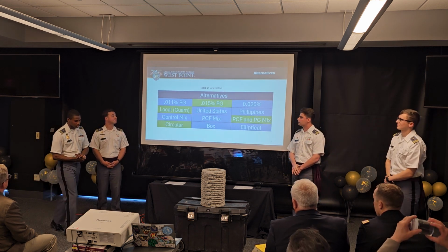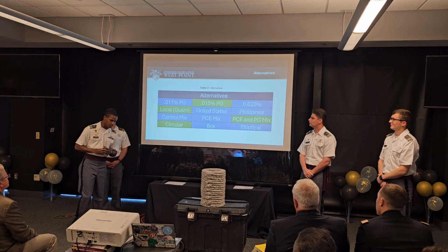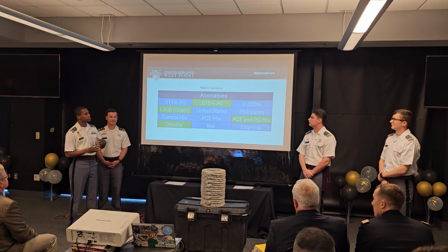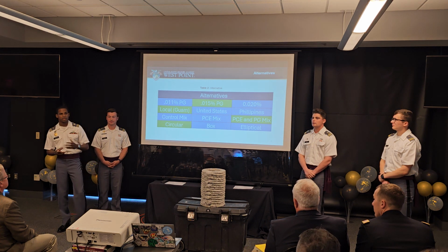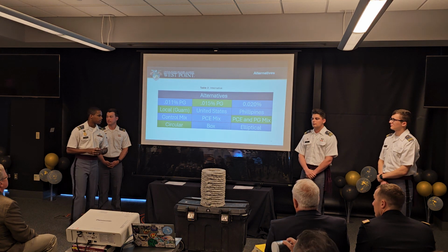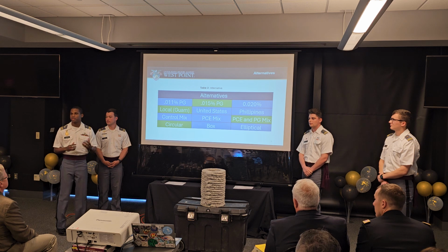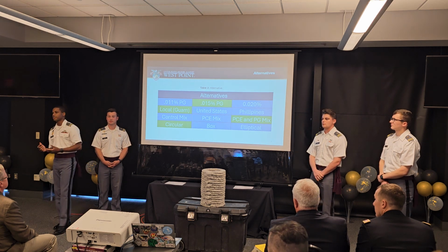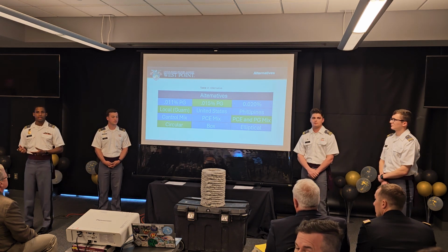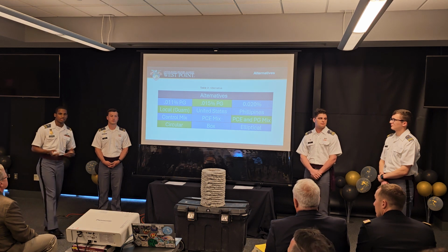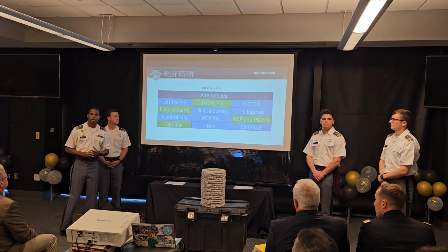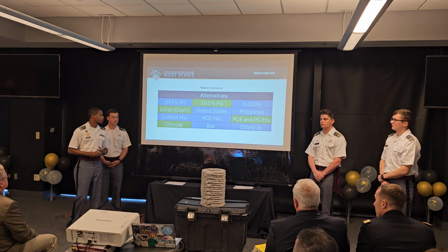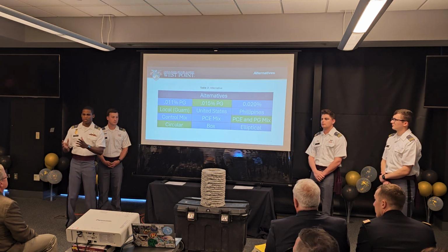Oh, so our alternatives, right? We had alternatives, for the first row, you can see our alternatives, the amount of pristine graphene, we talked about that in the EDSL, that was one of our characteristics. So we used the 0.011%, 0.015%, and 0.020%. We went with the 0.015%, Nick will go through that a little bit more later about why we did that due to structural strength.